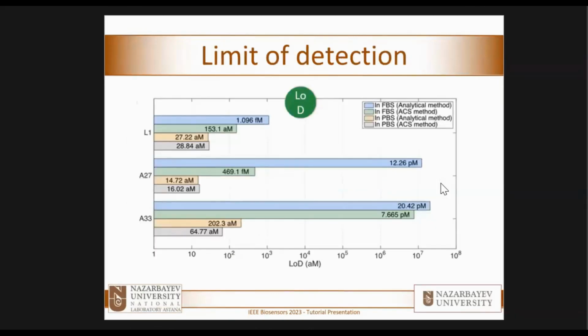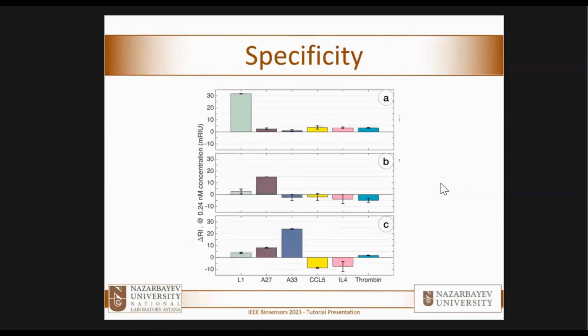And here it comes with the analytical limit of detection that were performed. So in PBS, of course, they're very low. PBS is quite ideal. When you actually change the medium, they're still quite good one. So that's a very attractive type of sensor. So the proteins are recognized very well. And we could test the specificity, both internal, where basically we compare the antibodies bind to each of the protein to the antibodies bind to the other one, and with other external non-binding controls. The specificity actually is quite good.